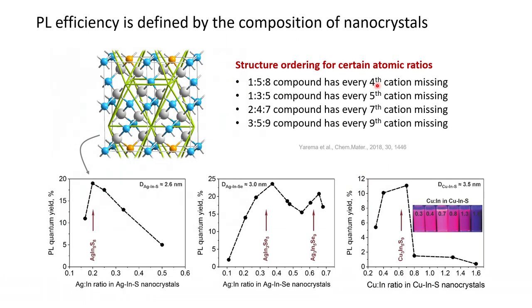We were not the first ones to find it, of course. So there is already this family of materials called ordered vacancy materials. For example, 1 to 5 to 8 stoichiometry of materials should have every fourth cation missing, which you see on this sketch. So there is an ordering of the vacancies in the green net. And this brings us to the best PL quantum yield. There are more of this family of materials, and the ordering for them is not yet known, and now we add yet another one, which has 4 components.